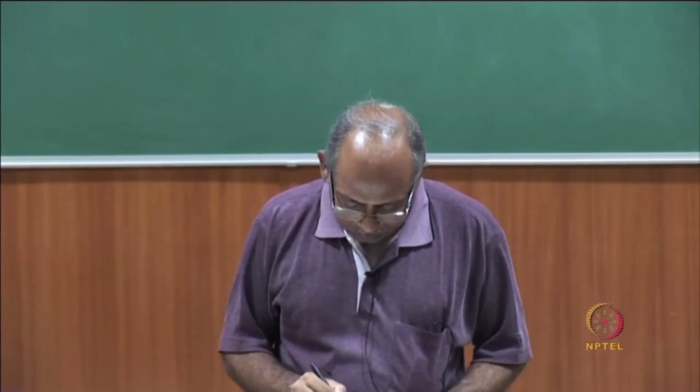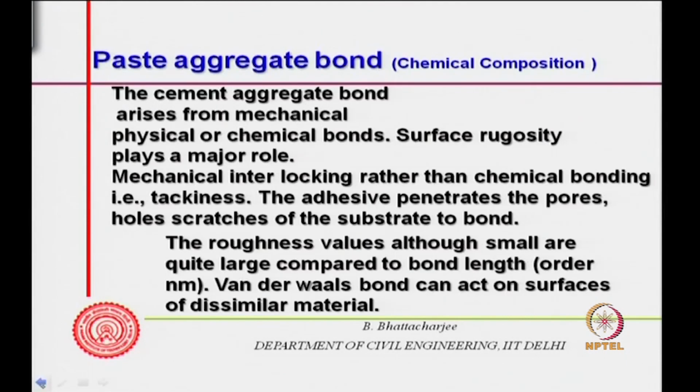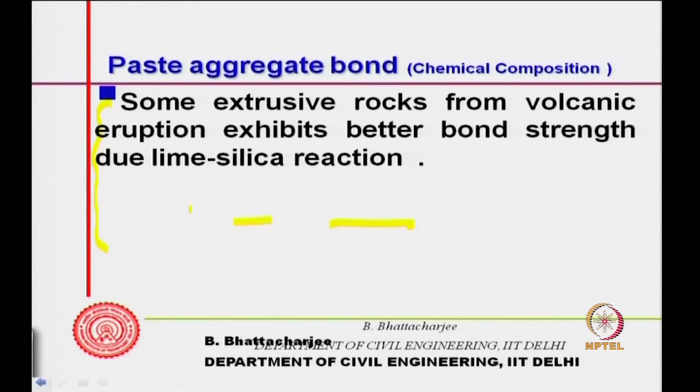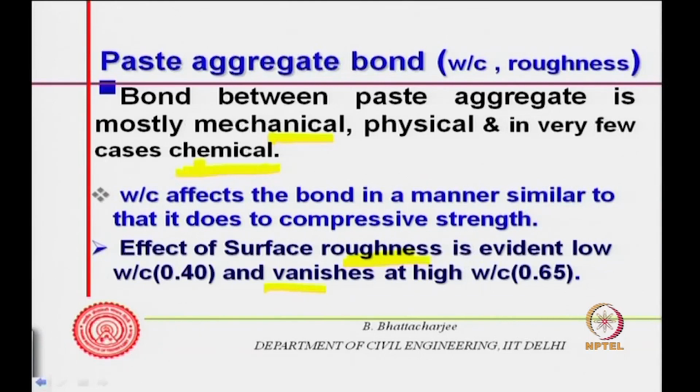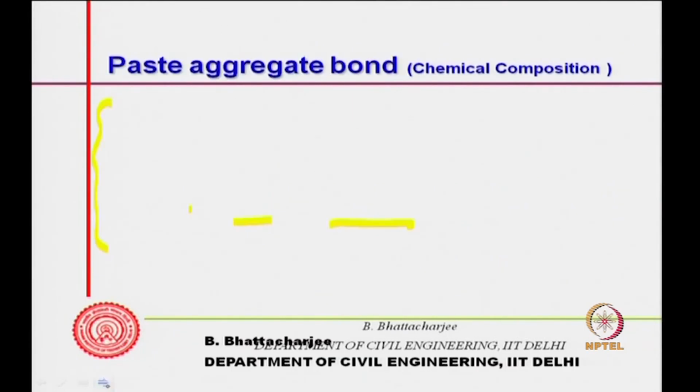Now, for a 0.4 water cement ratio, which I mentioned earlier, the reduction in strength because of surface structure could be as much as 70%.